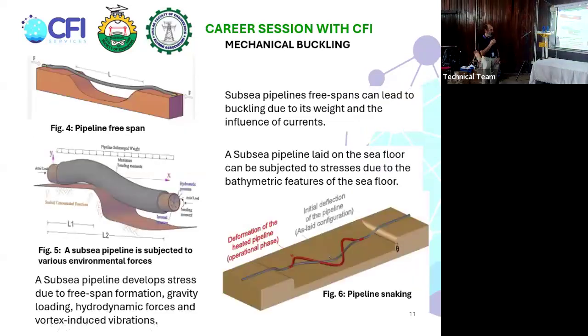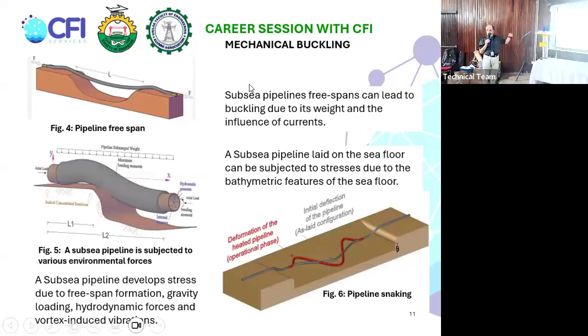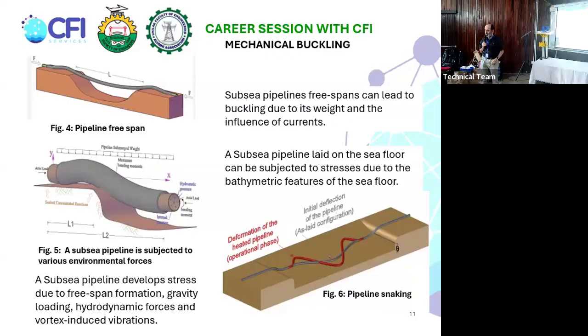Here are some examples of potential for buckling. The top one on the left, as I mentioned, is when the sea currents move away the soil that was supporting the pipeline. And so the pipeline now is in the air with a tunnel underneath that could be wide enough to make the pipeline unstable and make it want to fall eventually into that hole because of the weight, and then it can buckle. So that's called a free span pipe. It has no support, like a bridge with no support in the middle. So they can lead to buckling due to the weight of the pipe and the influence of currents.